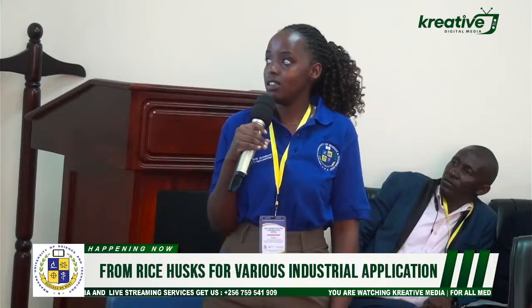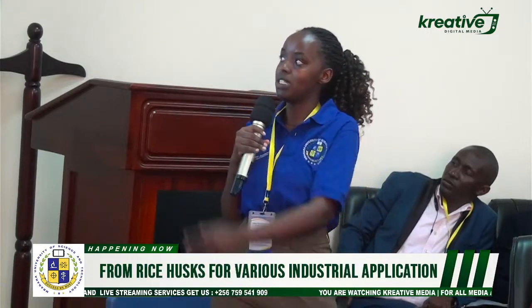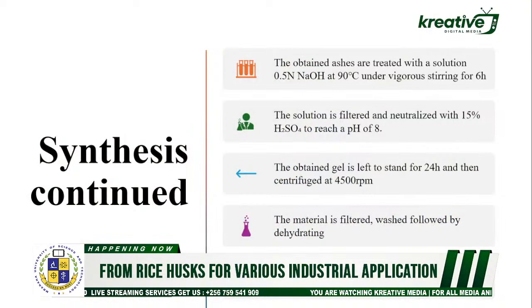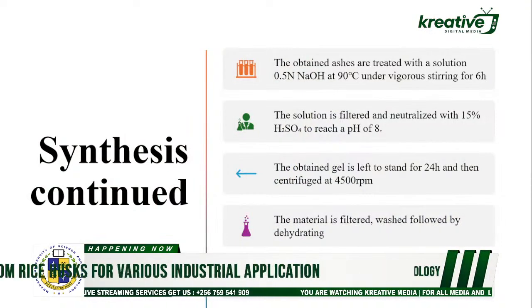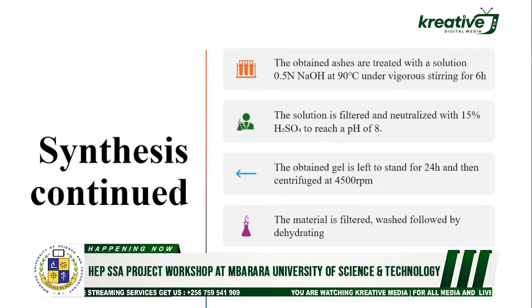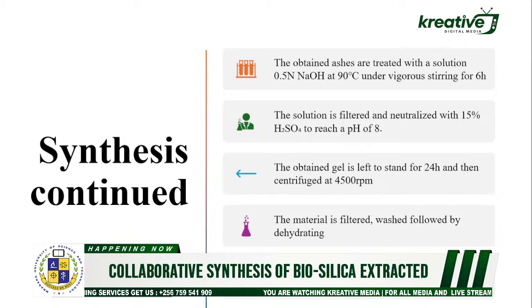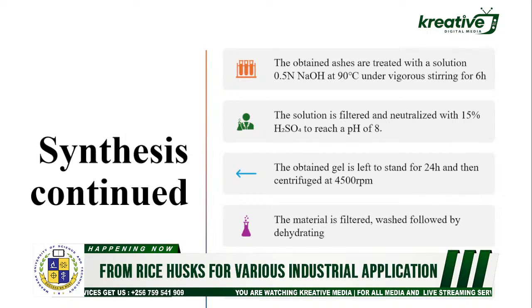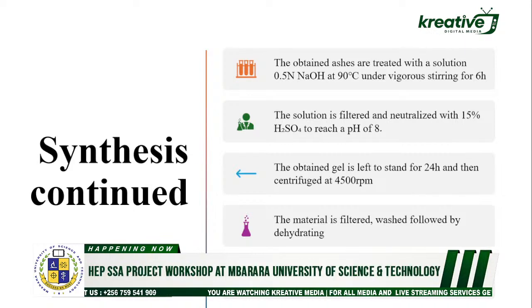So that obtained gel is left to stand for about a day, that is 24 hours, and then we do centrifugation to separate the precipitate, that is the gel, from the sulfate salts, from the sulfuric acid. And then we filter our material, wash it to remove the sulfate ions, and then dehydrate. There are very many ways of dehydrating, for example, freeze drying. And after that, we calcine our material once again, and we shall obtain the silica nanoparticles.